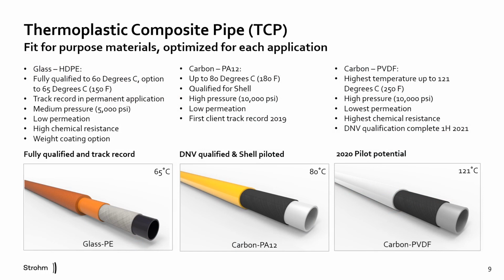The core of the product is based on proven and qualified fiber-reinforced thermoplastic polymers. To date, we have 3 options depending on your application. Our primary product line, and the source of our excellent track record, is our polyethylene pipe, which uses glass fibers for the reinforcement. Fully qualified in accordance with the DNV standard F119, it boasts a respectable top-end operating temperature of up to 65 C, and the maximum pressure, based on what we have supplied to date, of around 5,000 psi.